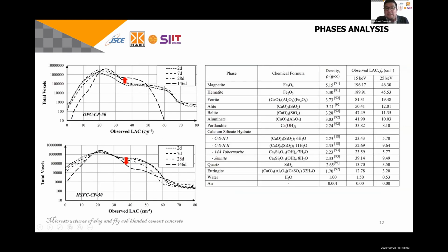From the histogram, you can convert into LAC, linear attenuation coefficient. From the study, we have the correlation between the LAC and specific items in the microstructure. For example, C-S-H type 1, here we use 15 keV, and the LAC value is around 23.43. From here, we could check the change in the microstructure during the curing period. As you can see here, we have two peaks: first the higher, and then the second is the lower. When you relate these to the LAC value, you will find what is growing.